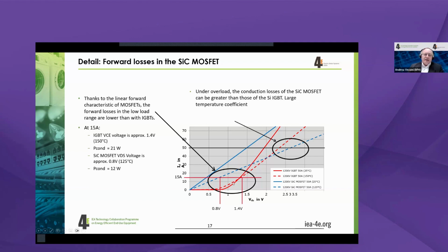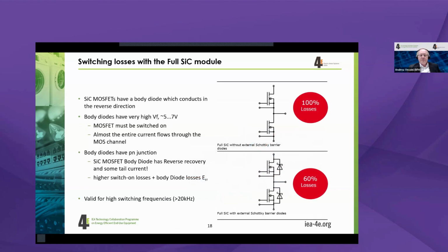What does it mean? It means basically, especially in low load or partial load, where you have lower currents than the nominal current, you will have a very good performance of the silicon carbide MOSFET, whereas at nominal current, especially at higher temperature, which will happen anyway if you operate at nominal load, you will have more or less equal conduction losses. If you look at switching losses, we see that the switching losses are very low compared to silicon.